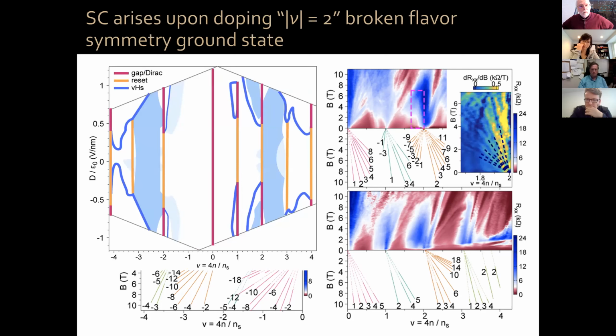Because you have holes, now they point towards the left. Okay, so what we believe is happening is that this Van Hove singularity here is triggering the phase transition, the cascade of phase transitions that typically occur at the integers due to Coulomb interaction. If you have a nearby strong Van Hove singularity, it can trigger that phase transition at an earlier filling factor. And because it occurs before nu equals 2, your reset sends you to the hole region.